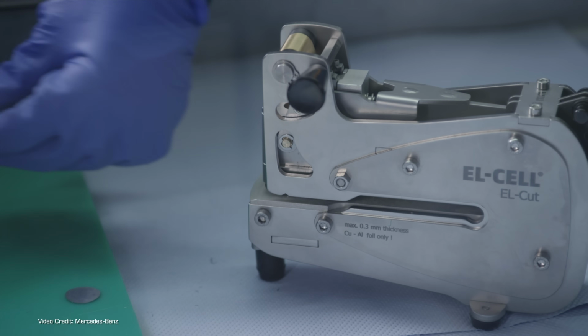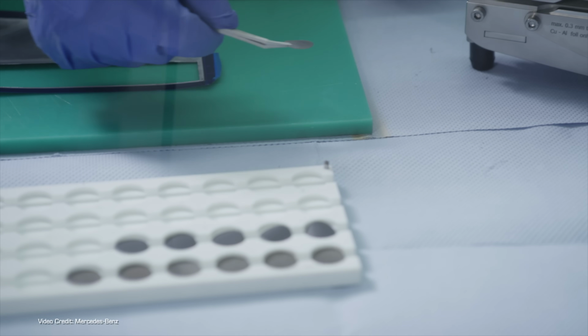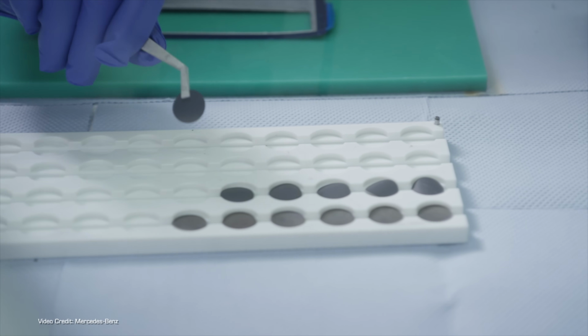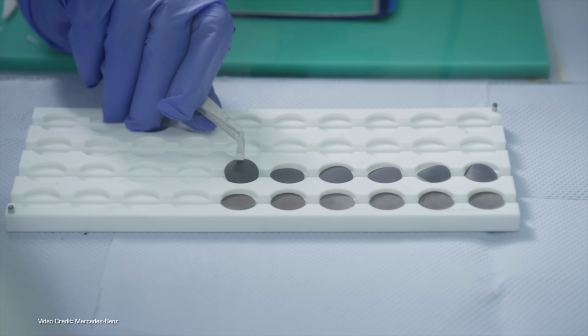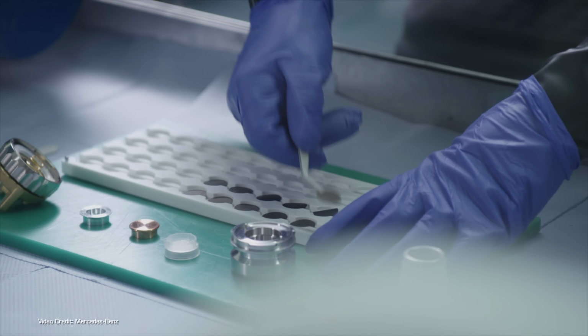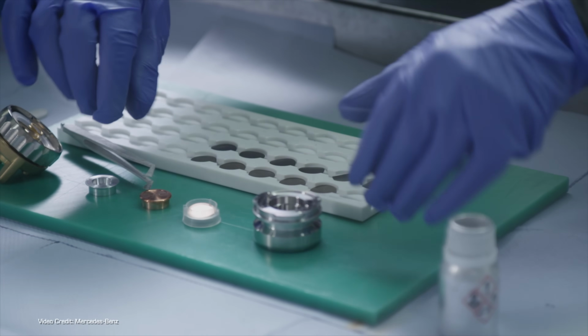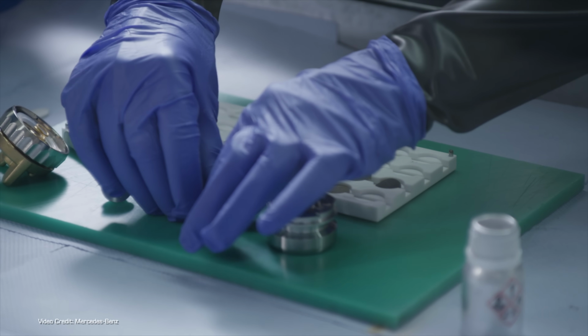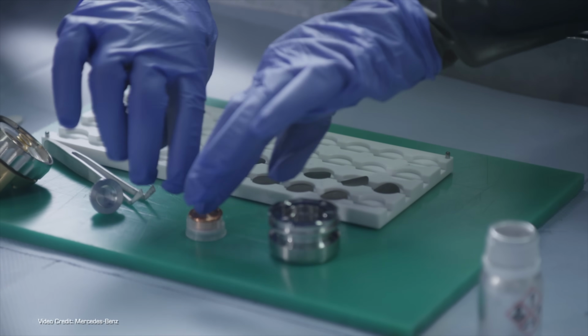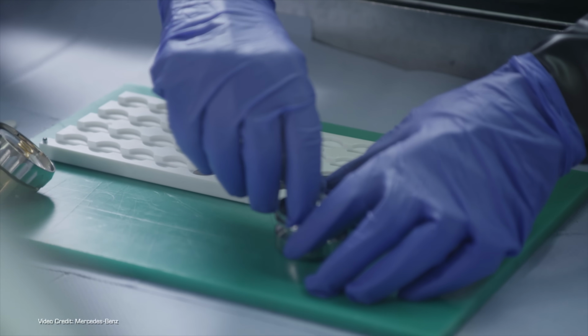A microscopic misalignment of a piece of production equipment that looks just fine to the naked eye may be enough to cause severe problems. It might be enough to exacerbate dendritic buildup on electrodes within the cell that are large enough to puncture through the separator material and cause internal shorts. Or it may be enough to create higher than designed internal cell resistances, heating up the cell more than expected during high charge or discharge events, prematurely aging the cell and accelerating its inevitable failure.